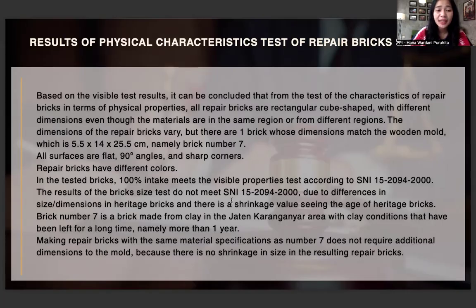But brick number 7 is a brick made from clay in the Jaten Karanganyar area with clay conditions that have been left for a long time, namely more than 1 year. Making repair brick with the same materials specification as number 7 doesn't require additional dimension to the mold because there is no shrinkage in size in the resulting repair bricks. So the result of physical characteristic, when we want to get the same like a wooden mold, we must use the material from Karanganyar, Jaten. Why? Because the clay condition that have been left for a long time, namely more than 1 year.